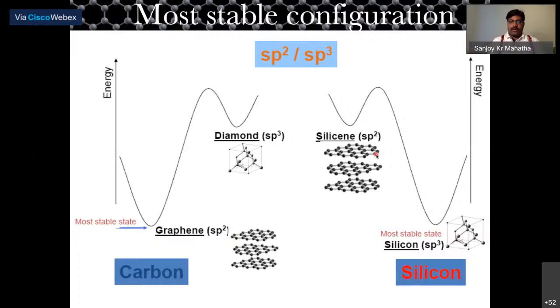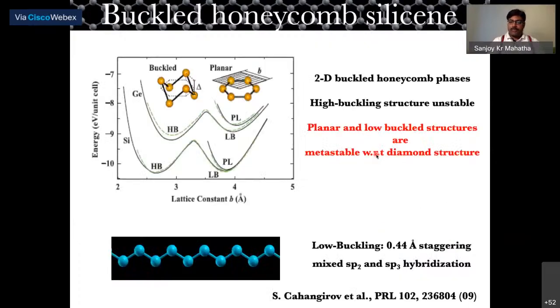So there are some theoretical calculations from 2009, and they calculated that because of this metastable state, there will be buckling of the honeycomb phase. These low buckled structures are really metastable with respect to structure, and the lowest possible buckling which was achieved was 0.44 angstrom with mixed sp2 and sp3 hybridization.